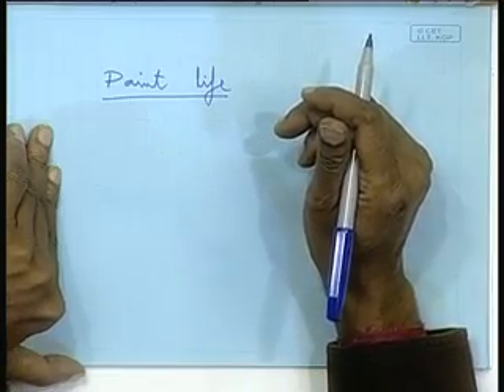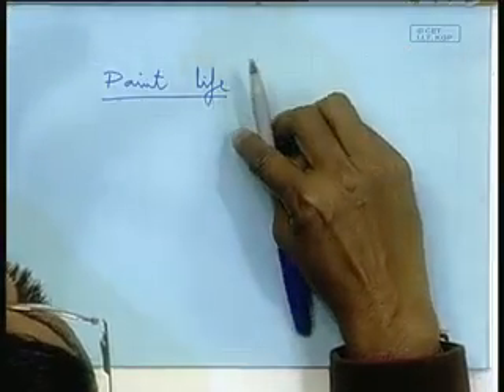If you have more corrosion, it means your operating cost goes up, the ship owner's operating cost. Why? One aspect is that the hull surface becomes rough, your resistance increases, your power requirement increases, and fuel consumption increases. The second aspect is that it is corroding, which means you will have to dry dock the vessel, clean the surface and then repaint it. All that costs money. If the corrosion is too much, maybe you will have to cut out that corroded part and put in a fresh new plate. All these are very expensive.